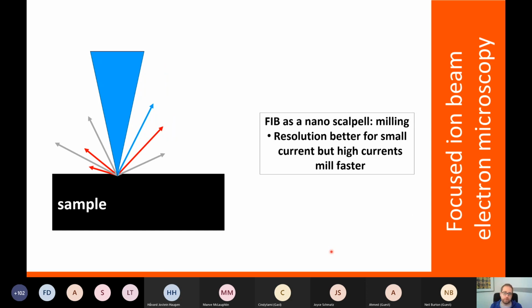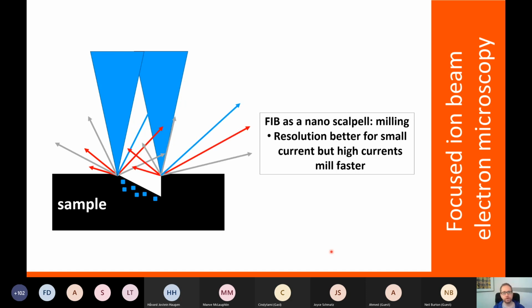So the FIB is like a little nano scalpel. You can actually mill into the material with extreme resolution. This is shown here. We can actually scan the ion beam across the sample and cut into the sample with extreme precision. And of course, the resolution of this cutting is smaller at lower currents, but it takes also much longer.